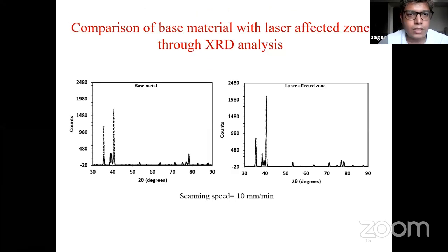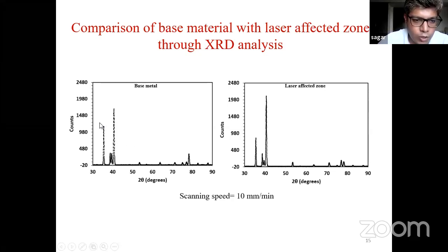After that I checked whether any new phase has been formed because of laser treatment. So I did the XRD analysis, X-ray diffraction analysis. Here you could see this is the 2 theta graph of the base metal, and this is the 2 theta graph of the laser affected zone. The peaks show the different phases present inside the material. If you don't get new peaks as compared to the base metal, that means a new phase has not been formed. However, this XRD analysis shows the results at gross level, that means at bulk metal level.